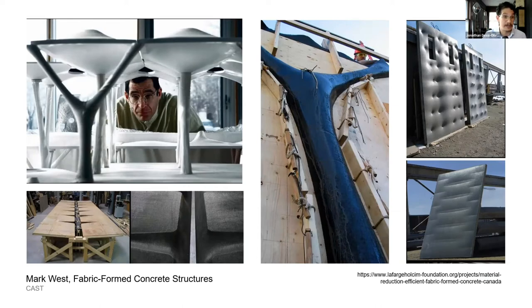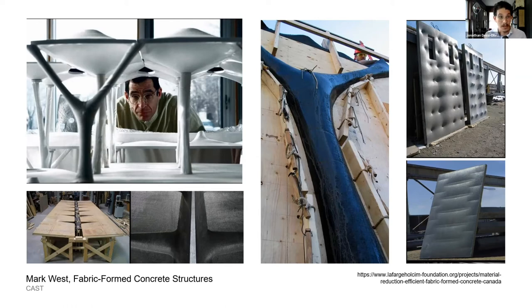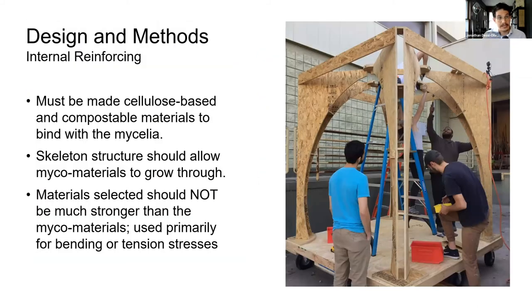On the inside, we took inspiration from Mark West, a pioneer in fabric-form concrete structures — a duality of formwork involving massive wood formwork alongside geotextiles that can make evocative forms in concrete. Because we were casting a very large amount of mycelium, we said: why not try to inherit some of the more experimental qualities of cast concrete and bring them over to cast mycelium? Like cast concrete, for the sake of safety, we included an internal reinforcing structure. Rather than reinforcing with steel, we reinforced with a cellulose-based material.